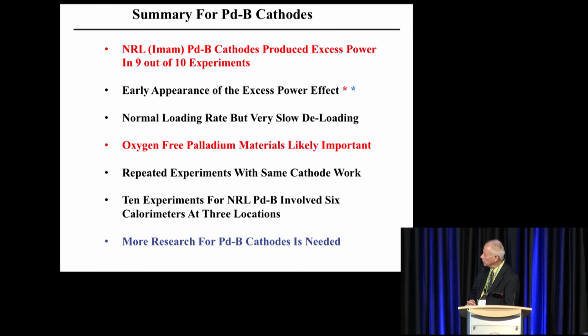why does the boron work so well? My thought is that it's oxygen-free palladium material. Like Dr. Imam said, when you make it, the boron will react with any oxygen. B2O3 is much less dense than molten palladium. It'll skim off the surface, and any oxygen is then removed from the material.